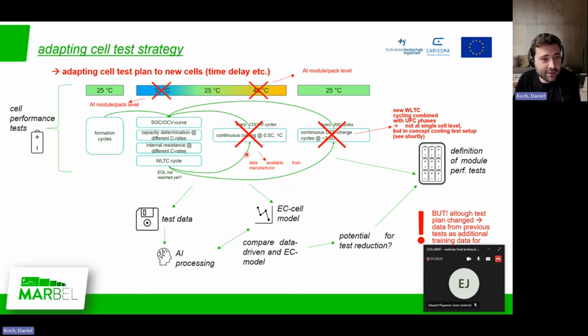So then we decided to cut a few of the tests at cell level and concentrate more on module and pack level later when they are assembled. And on the other hand, as mentioned, we adapted our ultra-fast charging strategy to a combined WLTC cycling strategy, which means we have continuous cycling with close to street WLTC cycles, and then we have interim ultra-fast charging cycles to evaluate the performance of the cells in these phases. On the other hand, we left most of the parts of the cell testing strategy.